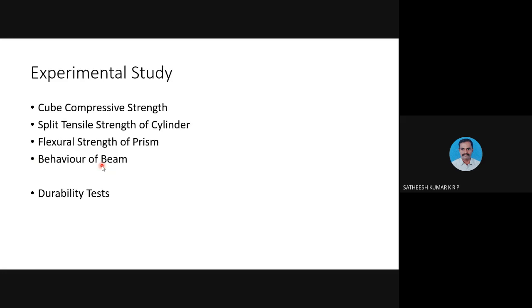And we observed that for high molar mixes, the beam actually exhibited ductility. In the sense, we observed more deflection before failure. Even though there is not a significant increase in the strength, like the cube compressive strength and the split tensile strength of the high molar solutions in this study, we can say like a 10 molar solution, 12 molar solution, 14 molar solution, those had a very close range. Even though the strength characteristics are much closer to each other, the deflection behavior was found a little different.